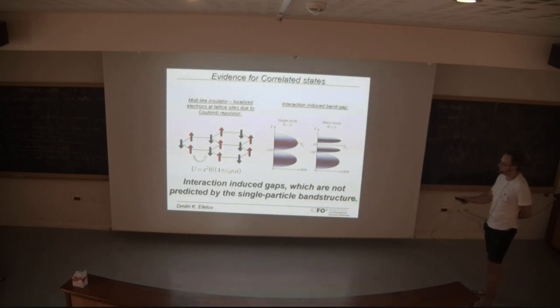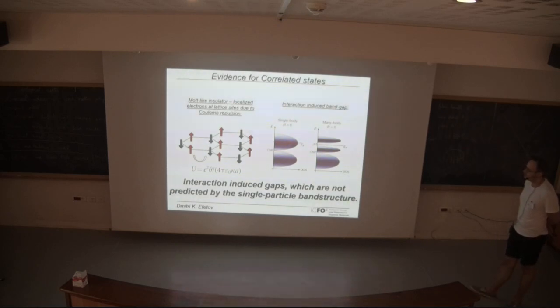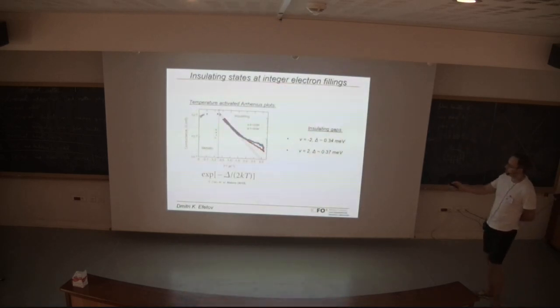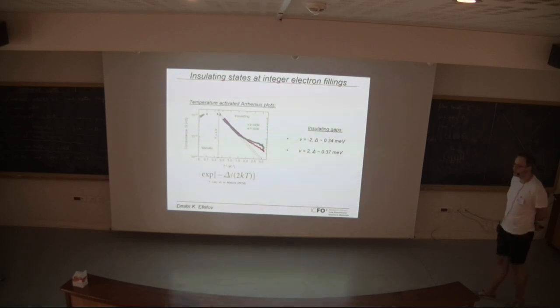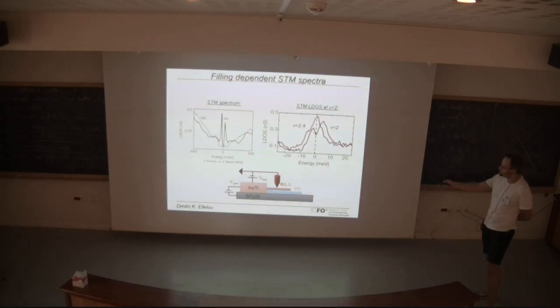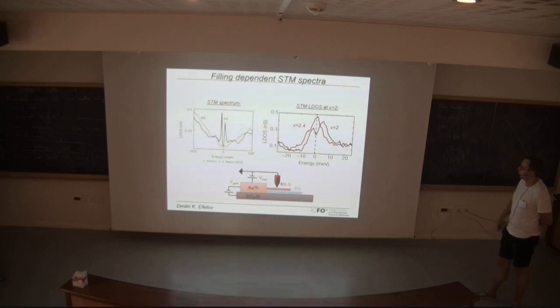So I think what I can confidently say is that in transport we see gaps at integer fillings. Then these gaps are also appearing in STM, whereas in STM they don't show a gap which completely goes to 0. They haven't measured the temperature dependence of it.